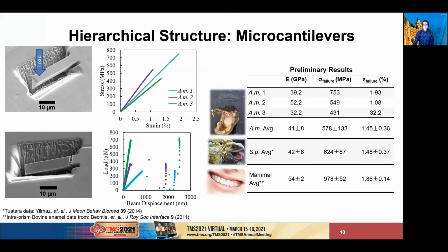One issue with characterizing hierarchical biological materials is it is difficult to deconvolute the contributions of each level of hierarchy to the total properties of the bulk material. Microcantilevers offer a potential solution for this dilemma, as the dimensions can be tailored to capture specific features at a desired size or orientation. These small cantilevers are fabricated directly into the polished enamel surface using a focused ion beam to mill out trenches of enamel at an angle, resulting in the triangular geometry you see here.